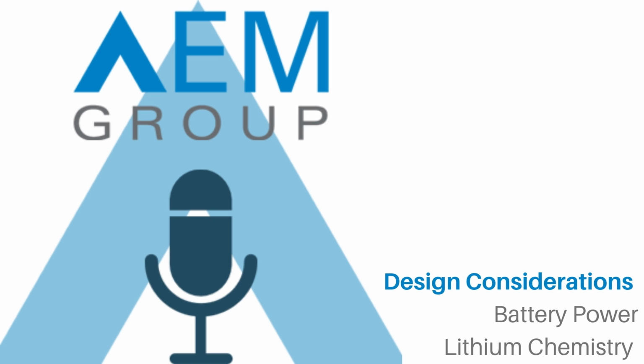Lithium titanate is comparatively expensive, and at only 65 watt-hours per kilogram, the specific energy is low, rivaling that of nickel-cadmium. LTO also charges to 2.8 volts per cell, and the end of discharge is 1.8 per cell. Lithium titanate is one of the safest lithium-ion batteries.